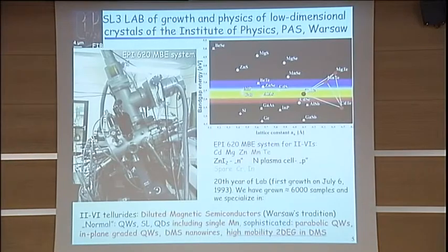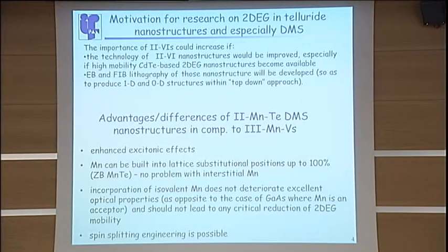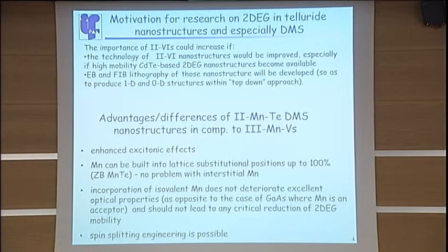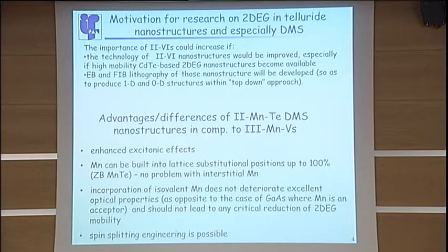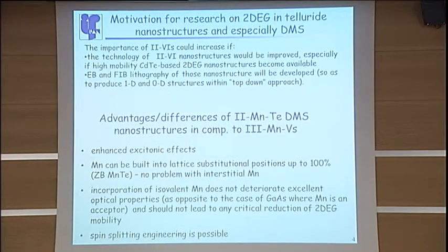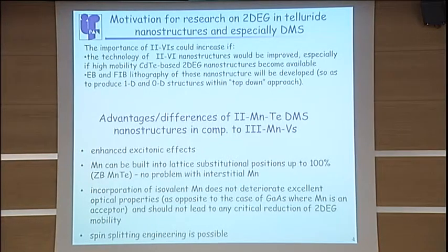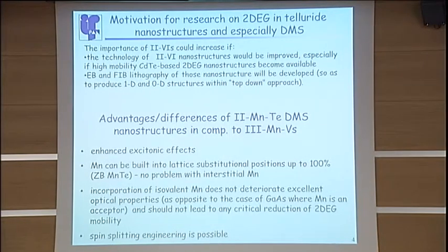So because those materials have some advantage over III-V. First, they have enhanced excitonic effects. Manganese can be built into the lattice into substitutional positions up to 100%. So for instance, one can produce zinc blende manganese telluride, which does not exist in nature. So there is no problem with interstitial manganese. Also, the incorporation of isovalent manganese does not deteriorate excellent optical properties, and we already have seen this in the case of cadmium telluride quantum dots with manganese, mentioned at the previous talk. And also, we believe that it should not lead to any critical reduction of the two-dimensional electron gas mobility. And I will return to this point. A very important advantage of these materials is that they provide spin splitting engineering.